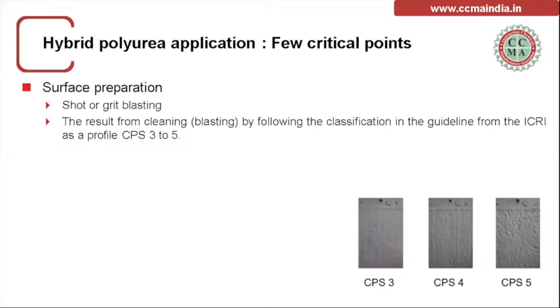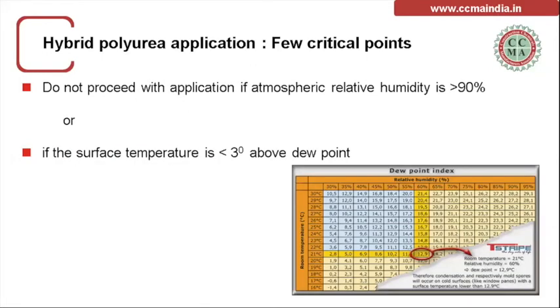Otherwise, the easiest and most popular method which has been used is grit blasting, captive shot blasting, to achieve this surface profile, which is the most important for the success of waterproofing membrane adhesion to the concrete surface. Apart from that, as I told you, the higher the technology, the higher the care should be to get the fantastic results we claim.